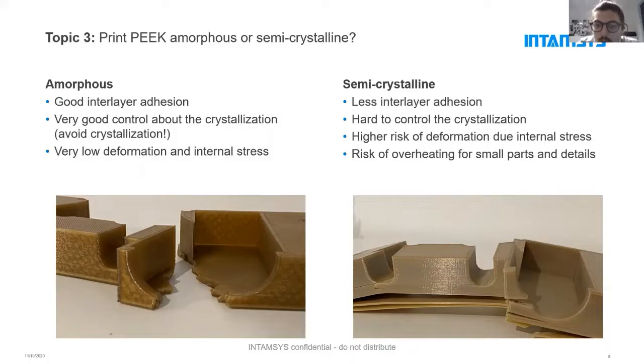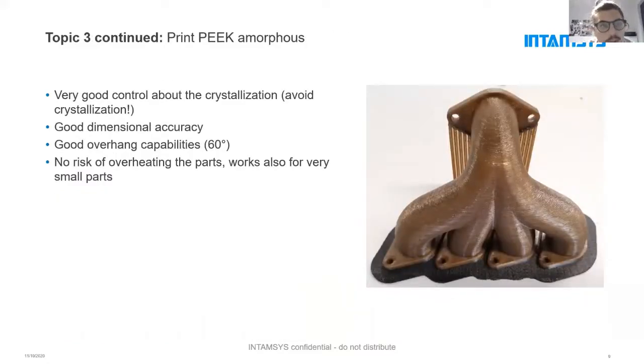The point is, due to varying geometry, you have varying heat input on the part, which makes it very hard to control the crystallization perfectly. And this gives you in the end a higher risk of deformation due to internal stress. Also, when printing with a highly heated chamber, you have the risk of overheating parts. So there's not only the risk of getting the parts too weak, there's also the risk to overheat them and get small details very bad. Also, overhangs are worse. So our recommendation is to really go with amorphous printing.